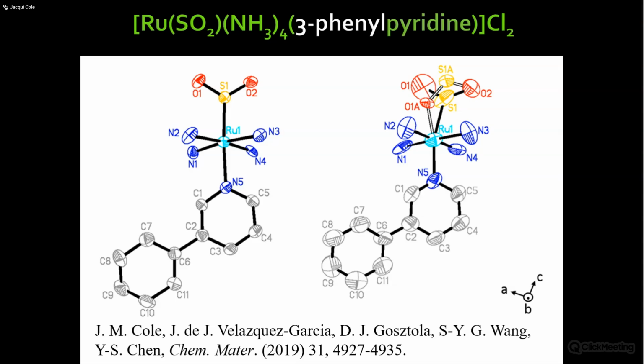I'll show you. So before I show you the actual example, this is the crystallography. This is the dark state, nice and ordered, as it always is before we apply light to it. And then we apply green light at 100 Kelvin, and suddenly all of these ADPs are much bigger. This is modeling the disorder, in this case a side. So there's your dark state, and it's being displaced by this oxygen-bound configuration here.